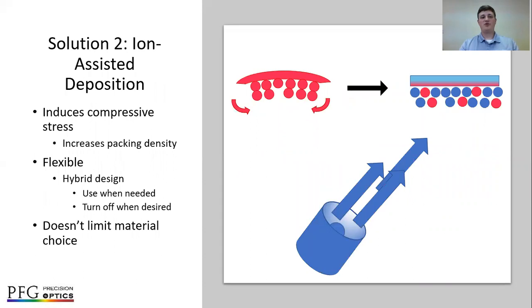The second thing we can do at PFG is use ion-assisted deposition. Typical E-beam or resistive evaporation produces tensile stress in the coatings. That's because these are low energy processes. In ion-assisted deposition, an ion source is added to the process to provide some energy and increase the packing density of the coating. This drives the stress in the more compressive direction with the goal of trying to achieve a stress-free coating. Now, there are other coating processes, for example, sputtering, that produce even more energy than IAD does. However, they're often too compressive, and there's not a lot that can be done about it.